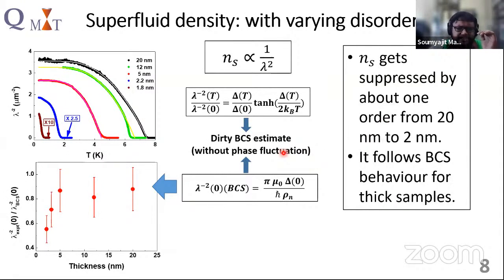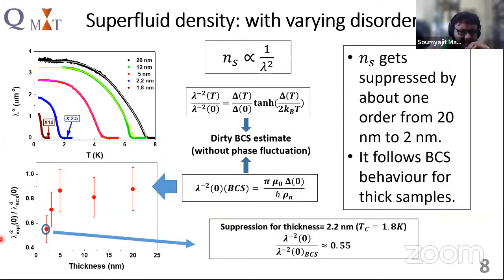And also we compared the zero temperature values of different thicknesses with the zero temperature BCS estimated value. As you can see from this curve, as we go to the lower thickness, it falls below the BCS value below 5 nanometer thickness, and also you can see that for the 2 nanometer sample it goes around like